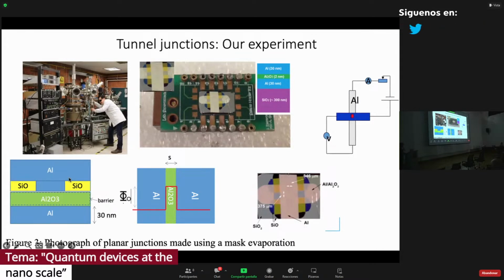You have to put also silicon oxide here to isolate these two parts. So there's a number of additional things that you need. And the measurements are 4-point measurements. You send current and measure voltage, here on the top right. Send current, measure voltage, and thus you get the IV characteristic, the current-voltage characteristic.